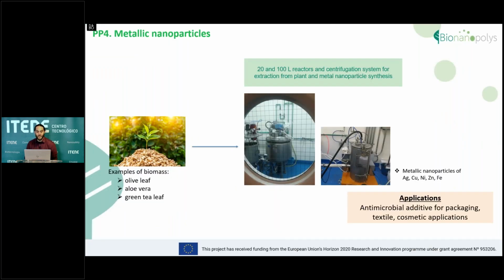Another interesting application is to use plant extracts like olive leaf or green tea leaf extracts to obtain polyphenols and cations that then can be converted into metallic nanoparticles in one of our reactors. We have capability for doing so in an ATEX chamber for 20 liters and 100 liters. And the metallic nanoparticles that we could develop here and deposit into other substrates could be silver, copper, nickel, zinc, or even iron. And these metallic nanoparticles could provide antimicrobial properties to textiles and packaging.